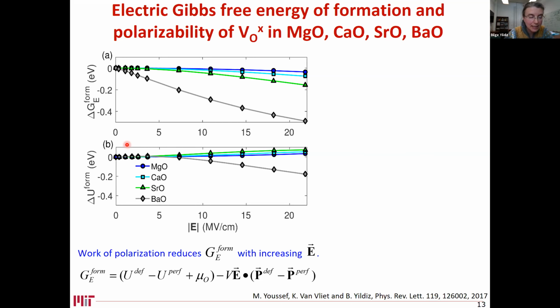What we plot here is the internal energy of formation and electric Gibbs free energy of formation for oxygen vacancies with trapped electrons as a function of electric field. So we contrast these two plots because by considering this polarization work, we can see that the two plots look very different, not only quantitatively, but also qualitatively. If we do not consider the polarization work, it appears that this defect becomes less and less stable with increasing field. But when we do consider the polarization work, the sign of the formation energy becomes negative and the defect becomes more favorable under increasing electric field magnitudes.